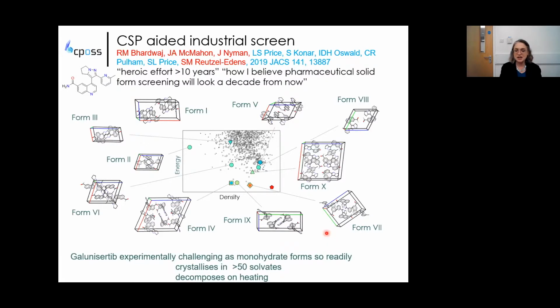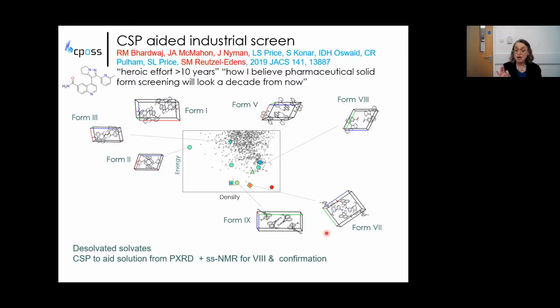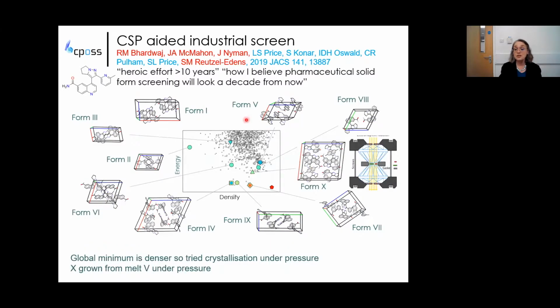The reason why this was so challenging is because it very readily crystallized with water in it as the monohydrate. And they're really interested to see if there was anything that rivaled the monohydrate stability. It would crystallize with virtually any solvent, and also it decomposes on heating. So this is rather difficult for polymorph screening, and only 2 of the polymorphs could grow classically from a solvent, a nice single crystal. So most of these crystal structures were desolvated solvates, giving rise to the different crystal packings, and they used our crystal structure prediction to help solving the structures from their powder patterns and solid state NMR. But there was this problem that we hadn't found what was predicted to be the most stable structure.